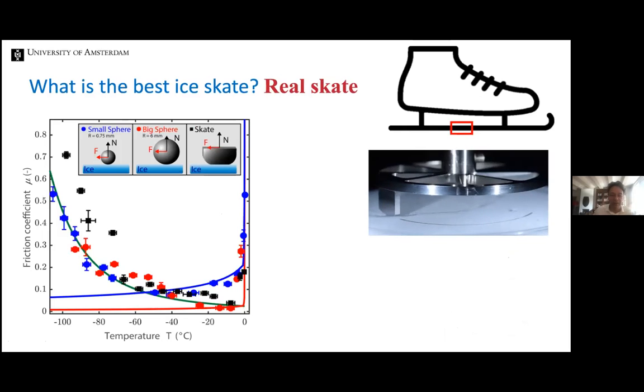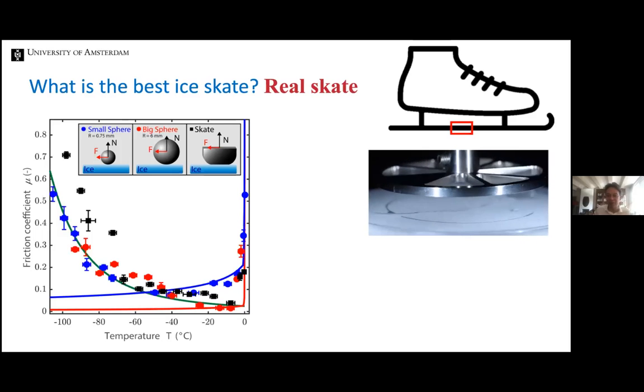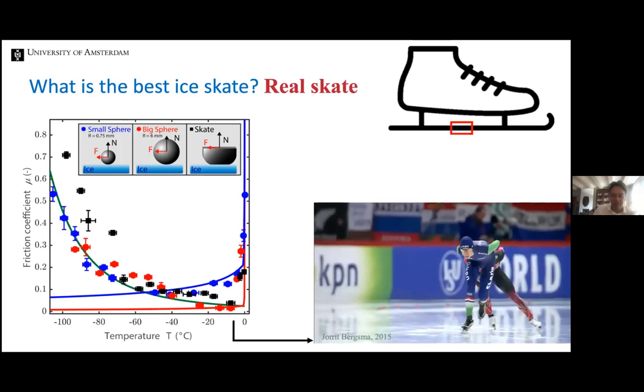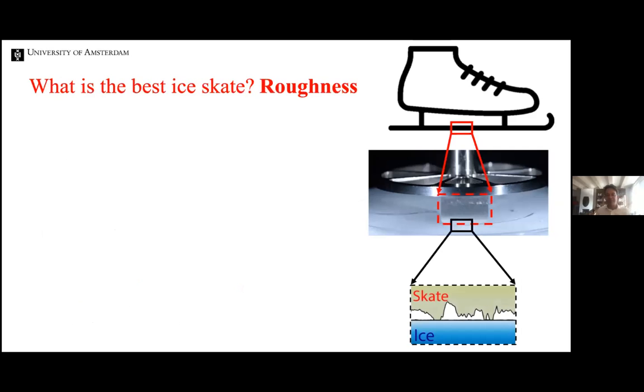because if you ask the people making the skates, they say the radius of curvature of such a skate is something like 10 meters. They have very precise machines that allow them to make such a very large radius of curvature over such a relatively small distance. If you look very precisely, you can actually see that the plowing is even less for the real skate than for the spheres. This was very informative, but it doesn't allow us to improve the skate for the skaters because they already knew this.